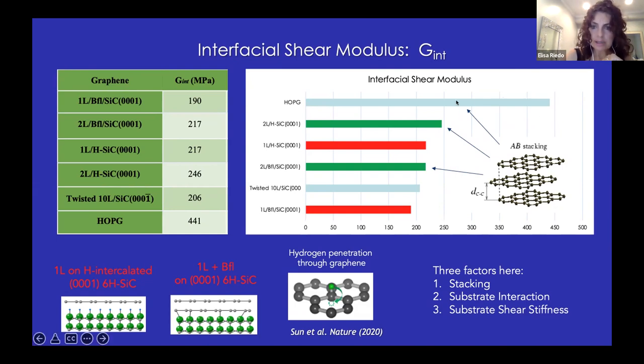For this reason, I indicated here the three structures that have AB stacking. So bulk graphite here has AB stacking, two layers on hydrogenated silicon carbide, AB stacking, two layers on buffer layer, also AB stacking. Now, as you can see, this is not enough to explain all our results because this structure here, which does not have AB stacking, in fact, one layer on silicon carbide doesn't have any stacking at all because it's just one layer of graphene, right? Still has a shear modulus that is much larger than one layer graphene on buffer layer. So why is this one layer on hydrogen, which is here, much larger than one layer on buffer layer?